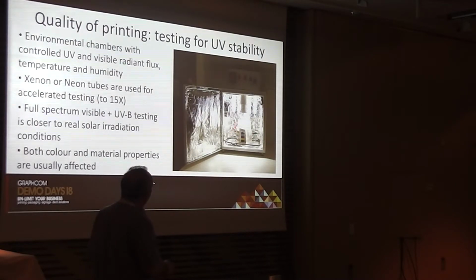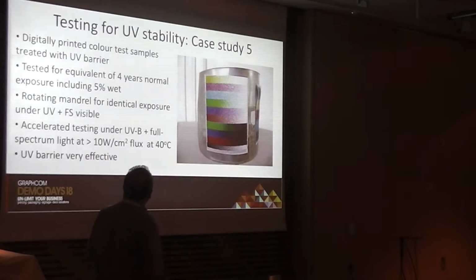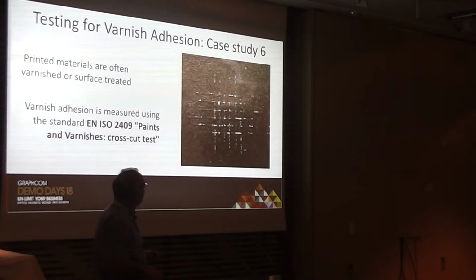And sometimes we do testing not only of the UV capability of the colors, which more often than not is what we're asked, but also of the material itself, because the material does not last very long under such aggressive conditions. And there's just a little test. This was accelerated, and we did the equivalent of 4 years of normal exposure in about 90 days. 90 days of exposure was equivalent to 4 years, and that was a very successful test as far as the customer was concerned. It was very happy.